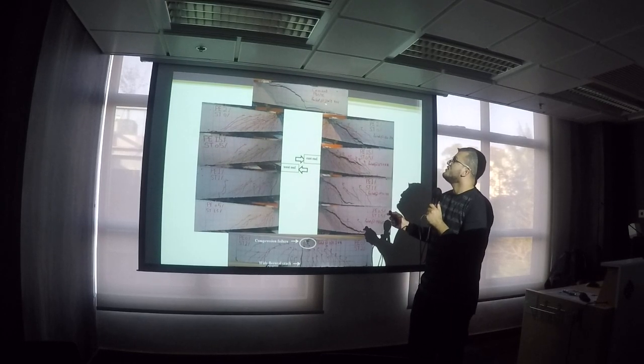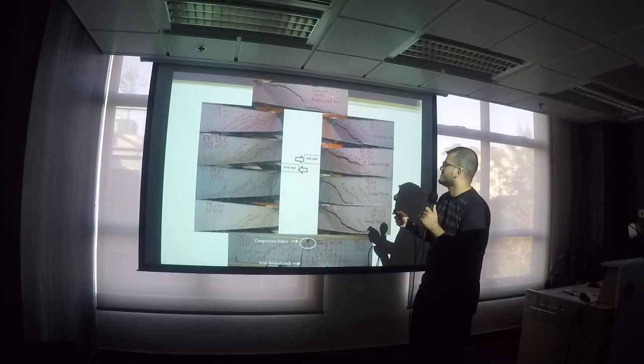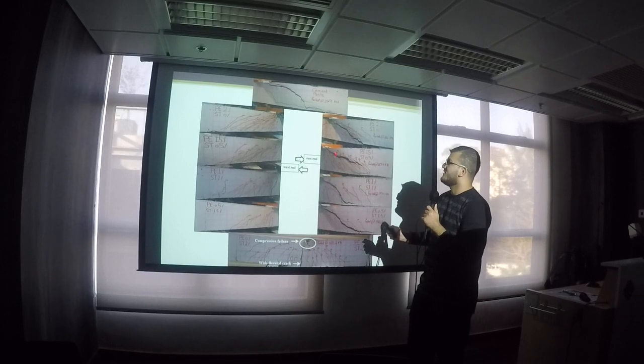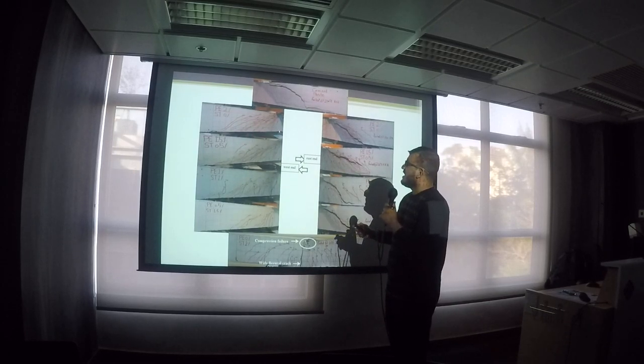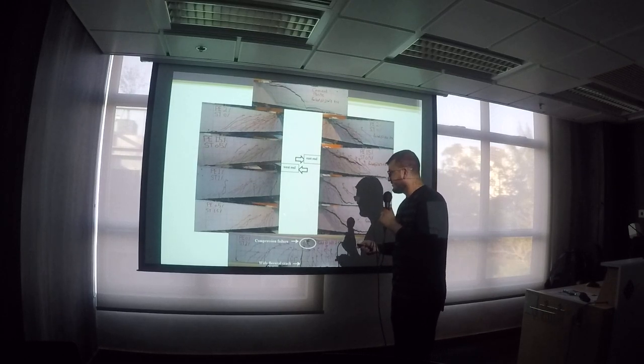So as you can see here, this is the control beam. The control beam has the typical shear failure with one single major crack. Actually, this one happened because of the extra loading at the end. While the other fibrous beams, as you can see, all have multiple cracking behavior. And again, what we can notice here is that the higher the polyethylene volume included in the beam, the higher the multiple cracking behavior. So decreasing the polyethylene volume will lead to decreased multiple cracking behavior. So here we have higher multiple cracking behavior and so on.